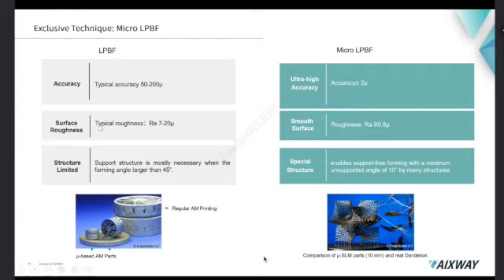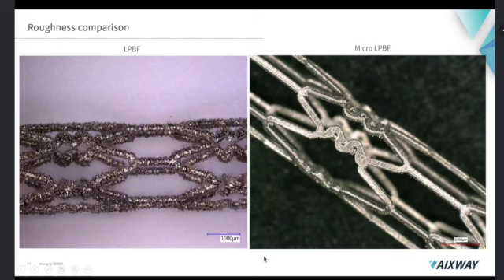Second is the surface roughness. Of course, the surface roughness is also greatly reduced. The typical roughness of our printed parts comes to a minimum of Ra 1 to 3 microns. You can see here in this comparison of our printed stents through the conventional LPBF and our micro-LPBF.